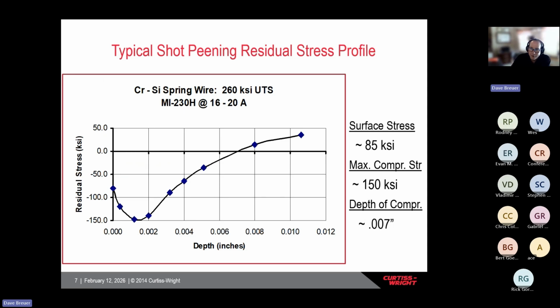Each of these measurements is done individually, and then they electropolish down to a depth and take another measurement, remove a little bit of material, and after doing this about 10 times, they piece the dots together to make the curve.